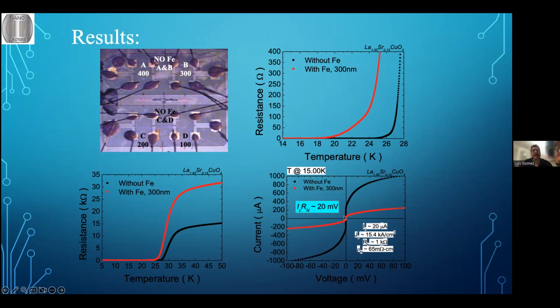So the one that has the iron, the critical current is much less, and also the resistance is much less. Well, actually I will have to get the dynamic voltage of this region here to find the resistance. But anyhow, here you can see that definitely the critical current is much less than on the other system. So let me see what values I get here.